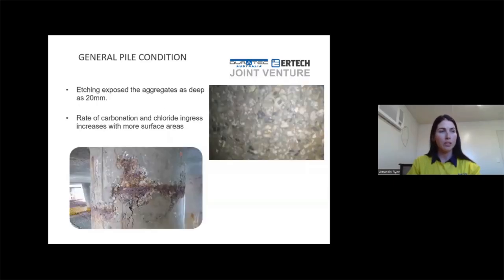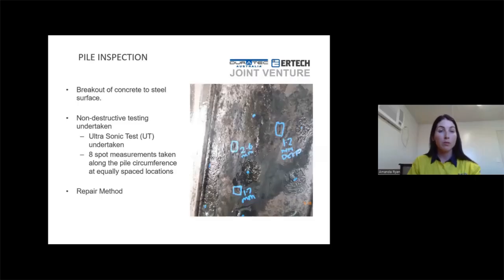So the pile condition, this photo here shows etching, with aggregates exposed as deep as 20 millimeter. And here on various piles, it showed carbonation and chloride ingress. Carbonation of concrete is a chemical reaction between carbon dioxide in the air and calcium hydroxide. It's mainly when the passive layer breaks down due to the carbonation, the bond between the steel and the concrete is broken. So we did a further inspection on the piles.